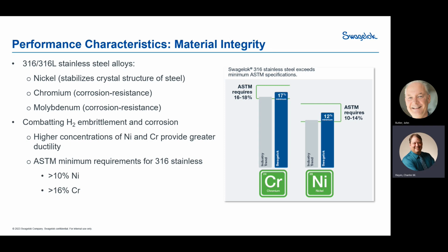Not in hydrogen. The problem with hydrogen is hydrogen starts affecting materials up until you have 12% nickel in there to stabilize the crystalline structure. So anything below 12 really is susceptible to hydrogen coming in and affecting the way that material works. So what Swagelok has done is set our material standard at 12% nickel. You'll hear other numbers in the industry sometimes. Sometimes people are touting 13. It's really not necessary. We found that the benefits of going up to 13 are negligible. It's kind of when you get on that high end of the curve, moving from one number to another can be very costly to get a very, very small increase in performance. And that's what we see.